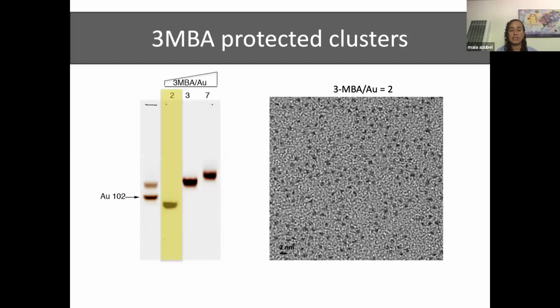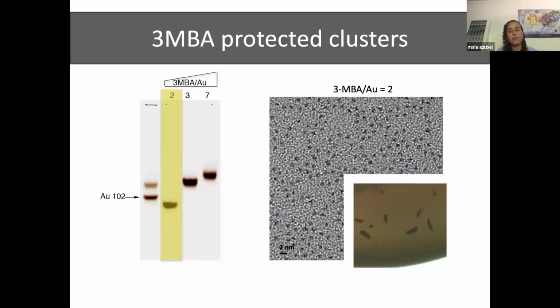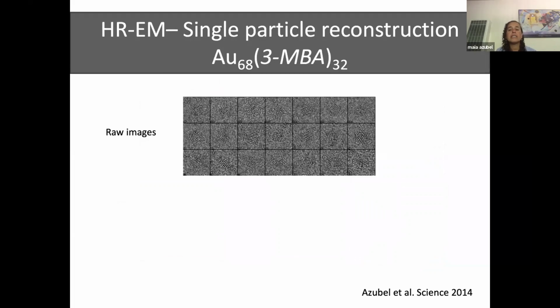The first one is the small guy that I used to call 3 MBA2, it ended up being the gold 68. And the other one is the largest that ended up being 144. Again, these 3 MBA2, I showed you the crystals before, but they didn't diffract. And this is how the image looks of the 3 MBA particles with 68 atoms. And I don't know if you can clearly see the white dots that are the atoms of these clusters that I imaged with the aberration corrected microscope, but that's why you do averaging.